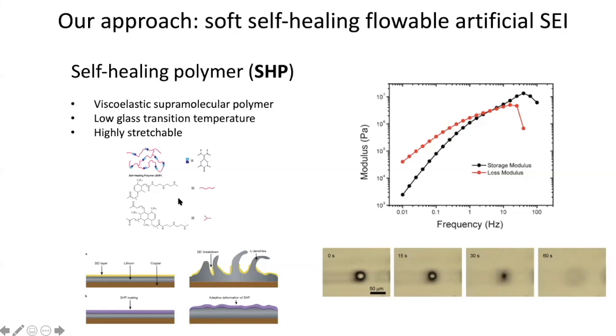Here, our rationale is that the dendrites are formed because as lithium gets deposited, lithium also will grow in the layer thickness. And as it grows, it will start to generate some non-uniformity at the interface with the liquid electrolyte. This non-uniformity can cause the interface layer, I mentioned SEI earlier, to break. And once it breaks, ions can go to this opening very quickly, and then lithium will grow rapidly and immediately form this dendrite. So our thinking is, our self-healing polymer, if we coat the self-healing polymer here, even though